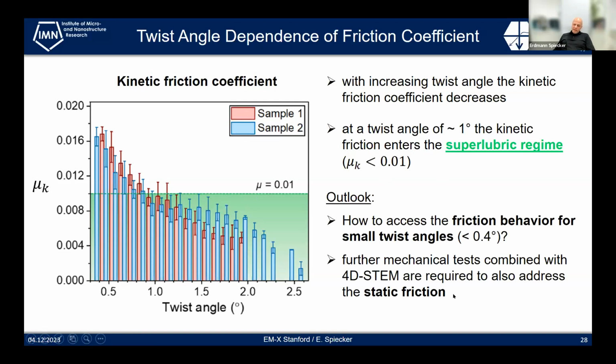And then we aim for further mechanical tests combining 4D STEM to also address the static friction. So you could imagine that you also kind of slowly strain the system, and before sliding action occurs, you can already measure the straining during this period. This was not possible for these experiments, but in principle, you can independently determine static friction and kinetic friction.